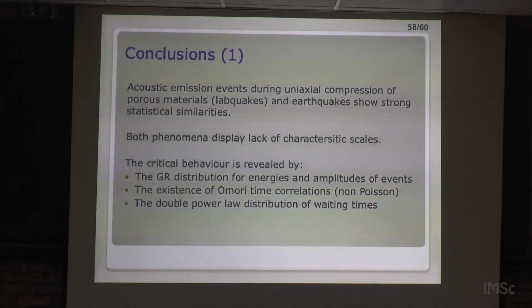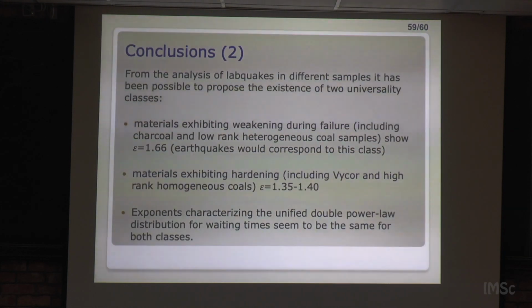Okay? So, and that's just the conclusions. Essentially, we have shown that labquakes show lack of characteristic scales revealed by the Gutenberg-Richter distribution, the Omori time correlations, and the double power law distribution for waiting times. And also, from the analysis of coal and charcoal, we have seen that there are two classes: materials exhibiting weakening during failure, which include charcoal, have an exponent of 1.66, rather similar to earthquakes, whereas materials exhibiting hardening, which compare very well with Vycor, have an exponent of 1.35, and the exponents characterizing the unified double power law seem to be the same for both classes.